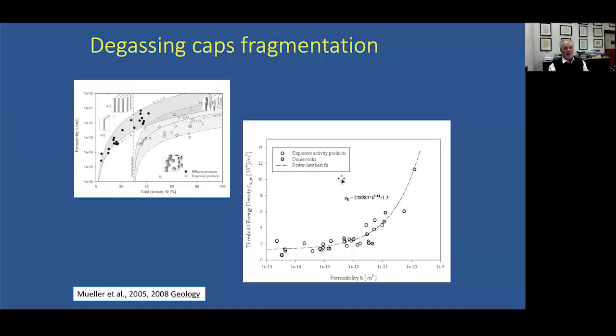A last picture from these fast experiments. We see here a specific energy as a function of what? As a function of the permeability, the speed with which gas can leave the material. And you see that there is no dependence of the energy density for fragmentation on permeability at low values of permeability, but as I drive to very high values of permeability, suddenly it runs away. Suddenly I can no longer talk about a specific energy density for a specific fragmentation behavior. And the reason that occurs is that simply the gas, which is under pressure in the pores of these rocks, is able to escape faster than the fragmentation front drives itself.